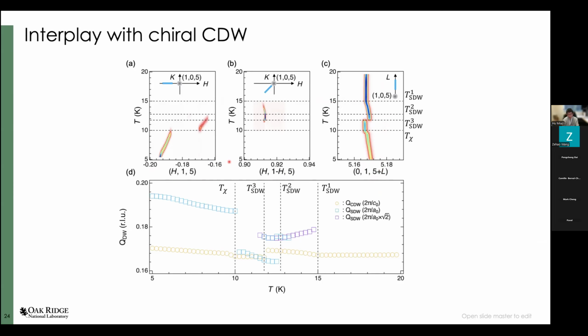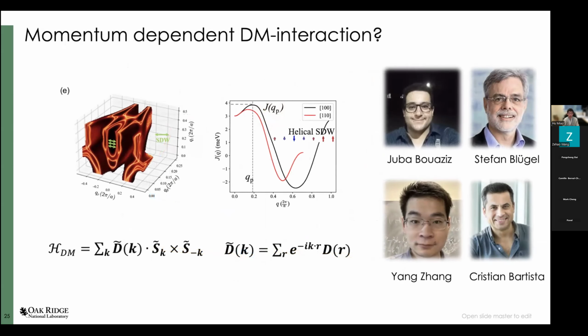So with all this experimental data, we started to ask our theoretical collaborators what drives the magnetic phase, and how do we explain the chirality flipping in the system? So Juba and Stefan performed first-principles calculations. What they find is that if you calculate the RKKY interaction, it turns out the helical spin density wave is indeed a ground state for this particular material, and they can even estimate the transition temperature, about 16 or 20 Kelvin, very close to the experimental value. Even the peak in momentum space is quite close to the experimentally measured value. So basically, these calculations confirm that in this material, the delocalized RKKY interaction is dominant and determines the magnetic texture